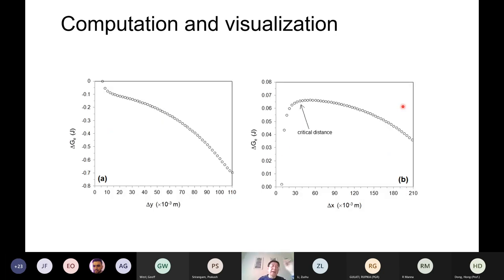So what he found is, for the first case, if the distance between those two inclusions is increased, that means they are separating, then the free energy is dropping. This is the electric current free energy, not chemical free energy. So it's dropping. That means electric current will try to separate those inclusions and prevent them from agglomerating.